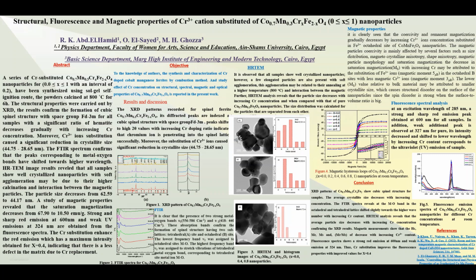A strong and sharp red emission observed at 600 nanometers and weak UV emission at 324 nanometers are obtained from the fluorescence spectra, which were observed after excitation at 285 nanometers. The chromium substitution enhances the red emission, which has a maximum intensity observed for the sample with X at 0.5, indicating that there is less defect in the matrix due to chromium substitution.